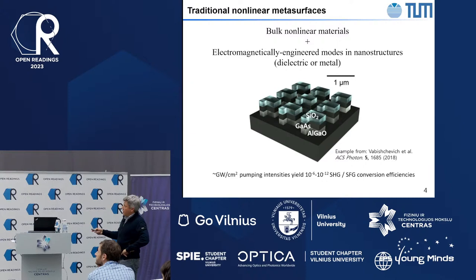Here you have essentially Mie resonators with a high dielectric material, gallium arsenide, at the center, surrounded by low index dielectrics on top and below. This resonator is shaped so that it has resonances at the input and the output, and that leads to an efficient light coupling from the input into the nonlinear crystal, and then the outcoupling of the generated nonlinear response into free space. Here they use the nature-given materials.